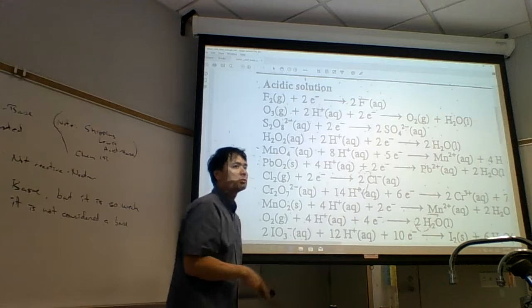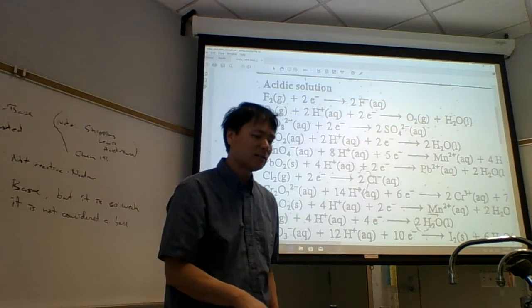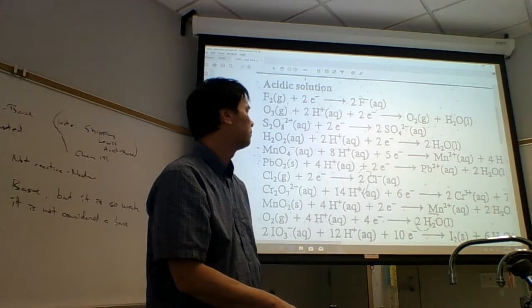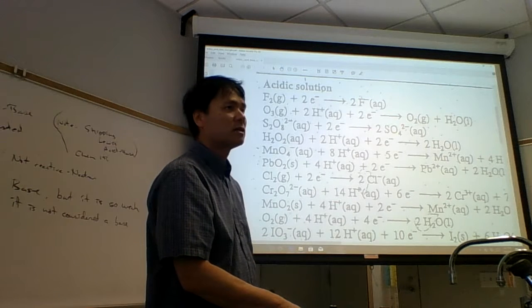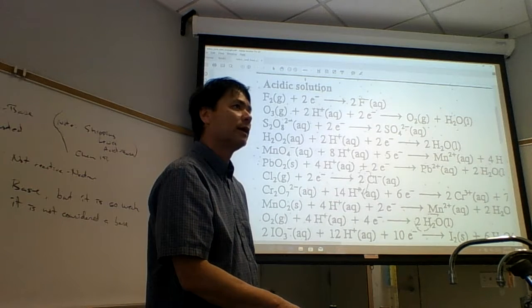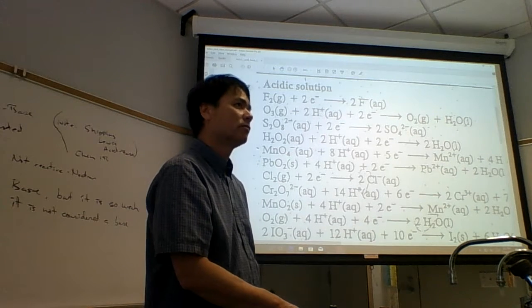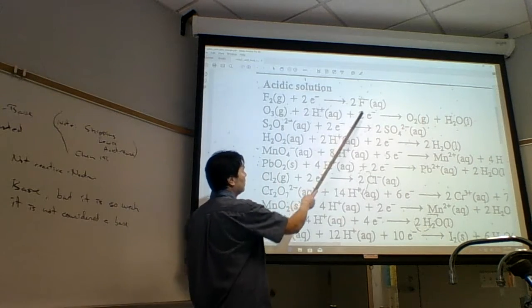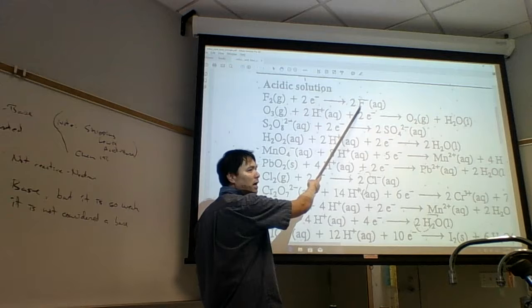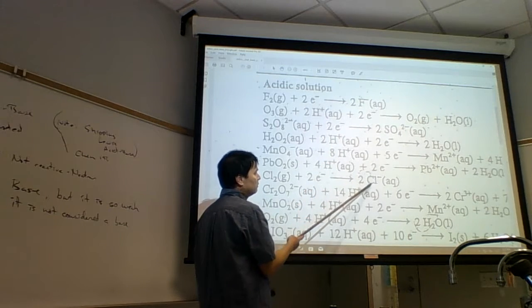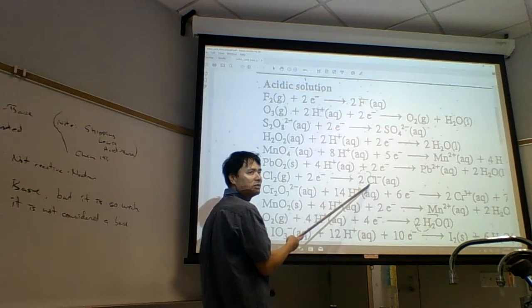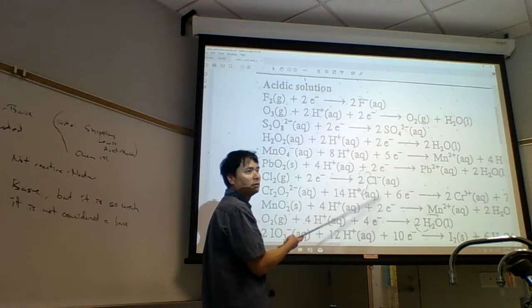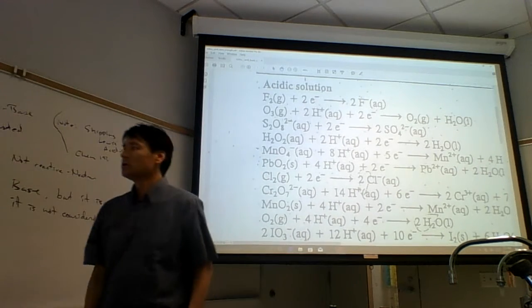I used Monel steel. Then I gently passivated the Monel steel so it wouldn't catch on fire. But the other components were eaten away, the valves. I had to replace the valves every week, because the fluorine would just eat them up. But anyway, fluorine is extremely reactive. That means fluoride is extremely unreactive. What about chloride? Chloride is unreactive.